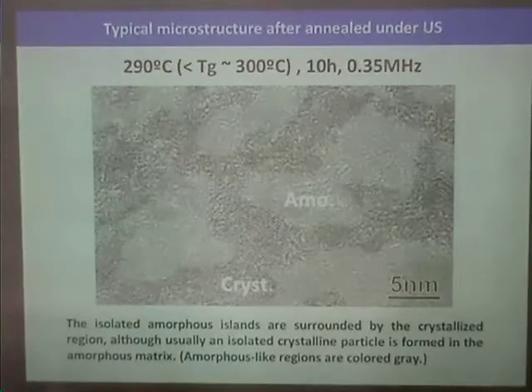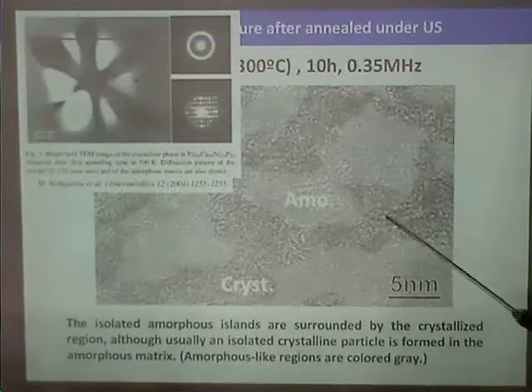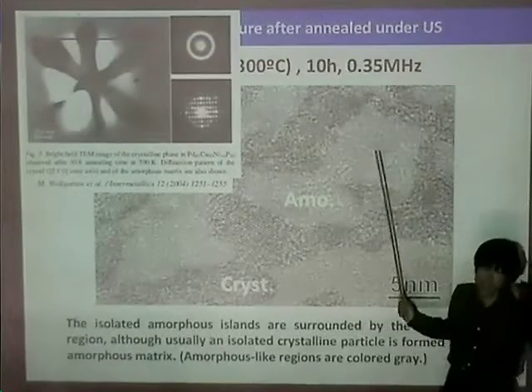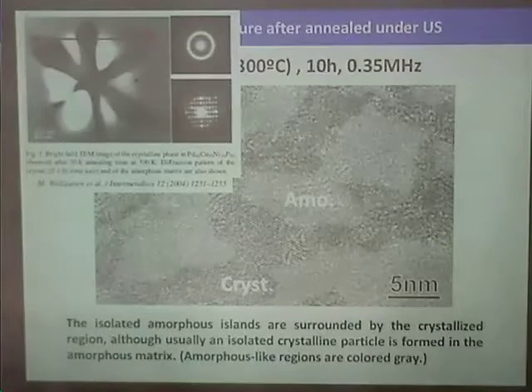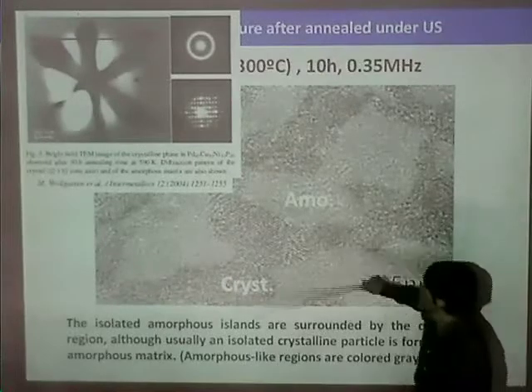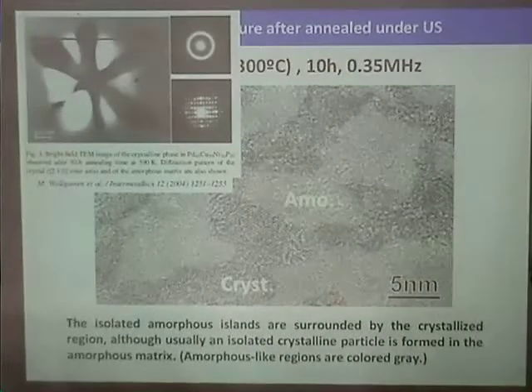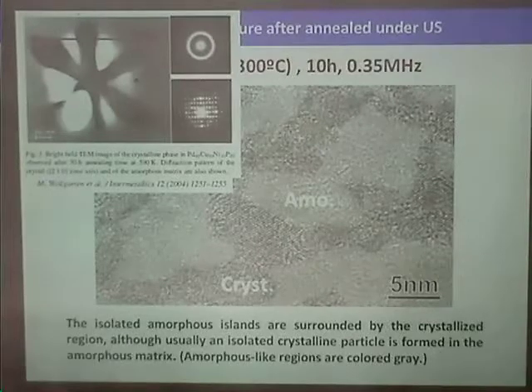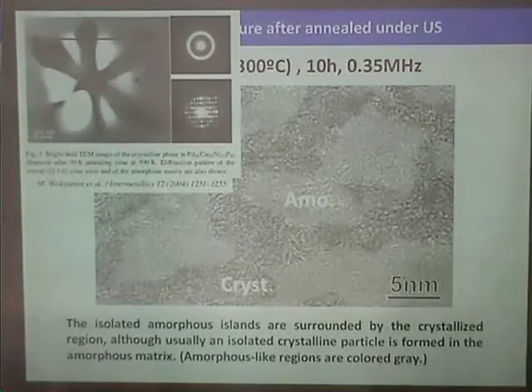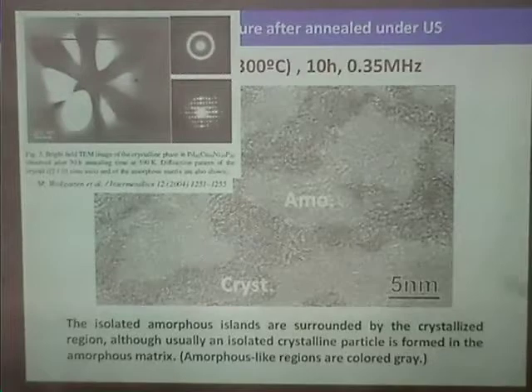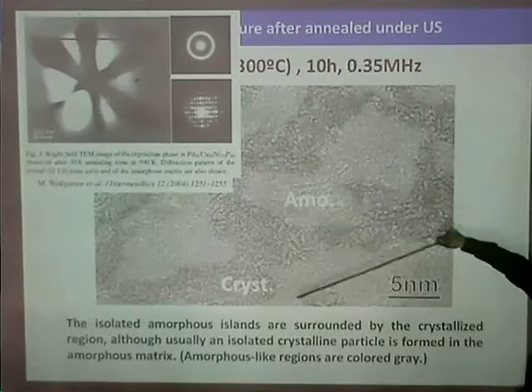Usually, when the sample is crystallized normally, above the glass transition temperature, a very large crystal of about 1 micrometer in size is initially formed. This is a typical characteristic of the palladium metallic glasses. But in this case, only several nanometers of crystallization occurs. The isolated amorphous islands are surrounded by the crystallized regions, although usually an isolated crystalline particle is formed in the amorphous matrix.